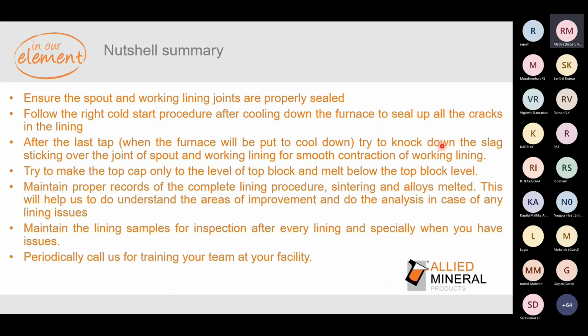We also recommend our customers to keep the spent samples, that is after 400 heats or 500 heats, for example. Try to store that lining sample from the side walls and the bottom, for at least 1 or 2 linings, till 2 or 3 linings have been completed in the same furnace. This will give an idea of how the sintering is happening, how the semi-sintered zone is there, how the cold phase zone is there. Based upon that, we can take a call whether we can extend the lining or not. So we can collectively work together to increase the lining performance based upon these things.